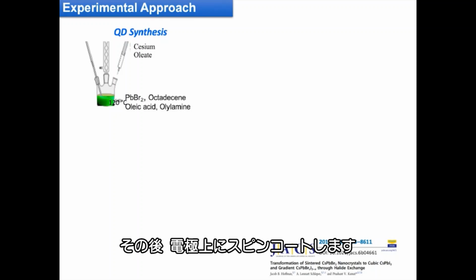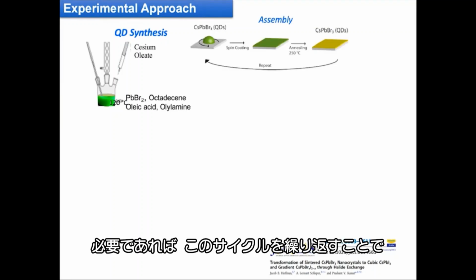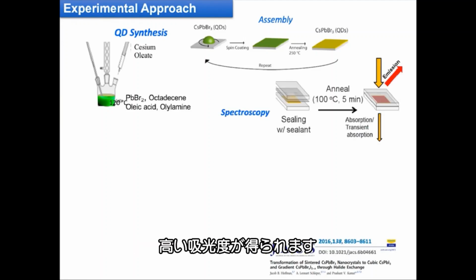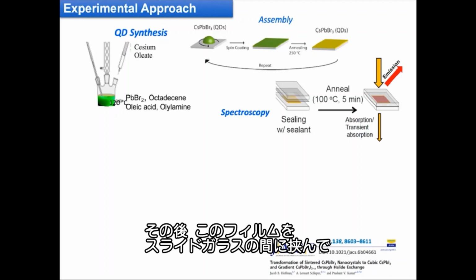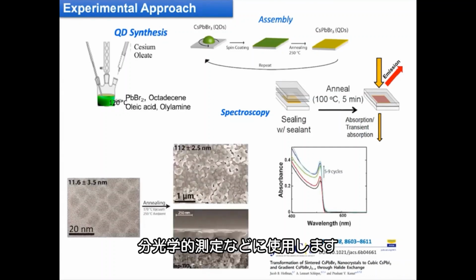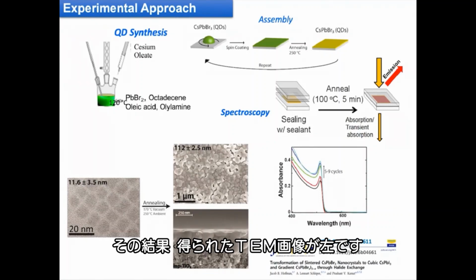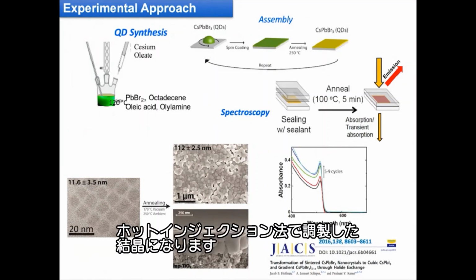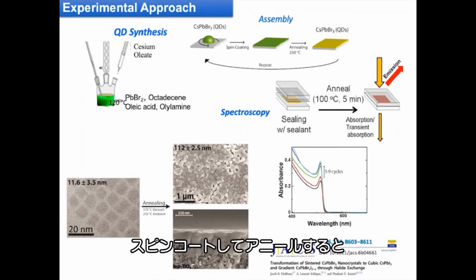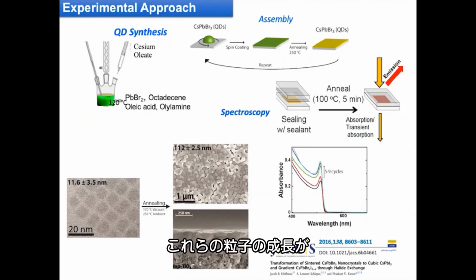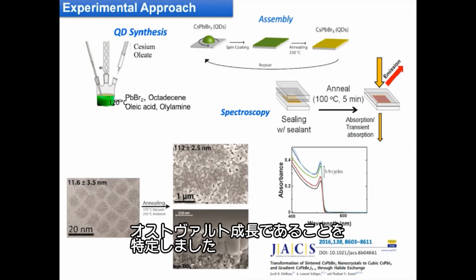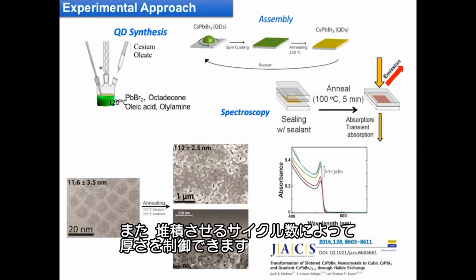Then we spin coat on top of the electrode, and we can repeat the cycles if needed to get higher absorbance, and then we put this film between glass slides for spectroscopy. Here is the TEM image on the left hand side of the crystals that we prepared by this hot injection method. But when you spin coat and anneal it, they grow to a size of about 112 nanometers. We identify this growth to be an Ostwald ripening process, and we can also control different thicknesses depending upon how many cycles we use to deposit.